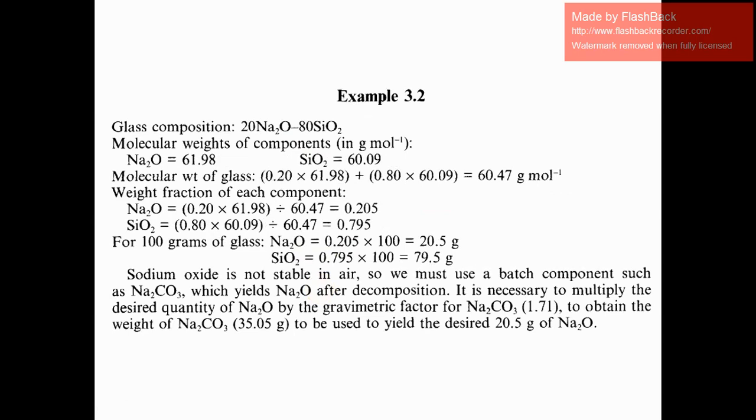But in this case, you can't take Na2O directly, because Na2O sublimes. Sodium oxide is not stable in air, so we must use a batch component such as sodium carbonate, that is soda ash, which yields Na2O after decomposition. You can take this raw material, and it will decompose in the tank furnace by removing CO2.